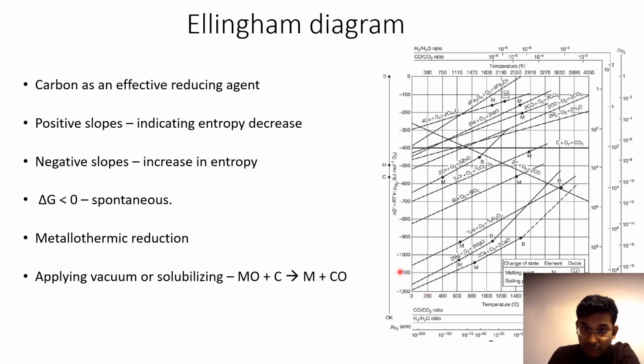So the ones at the bottom, you could see, have a lot of negative free energy. When something is negative in Gibbs free energy, it means the reaction is spontaneous. It means the compound is so stable that it is difficult to separate it from the oxide form. So for instance, if you have calcium oxide and aluminum oxide here, it's pretty far down, quite negative, which means that aluminum oxide is a very stable compound and you have to supply enormous energy to reduce it back to aluminum, okay? And the ones at the top are relatively easier.